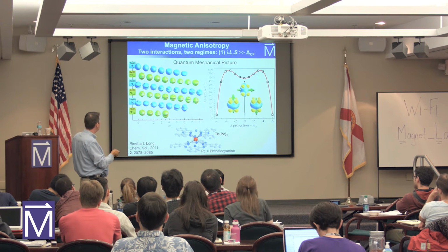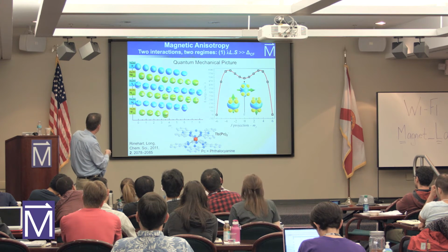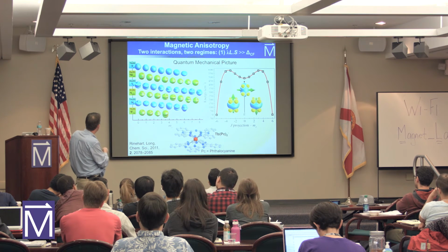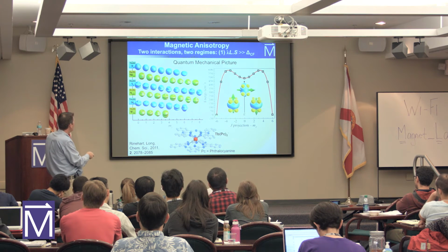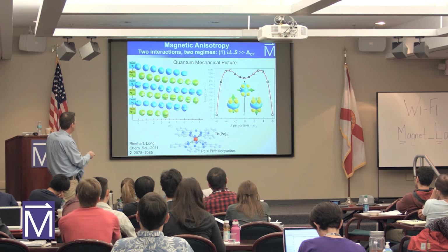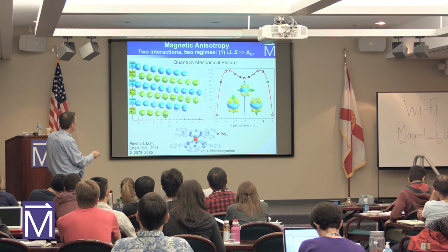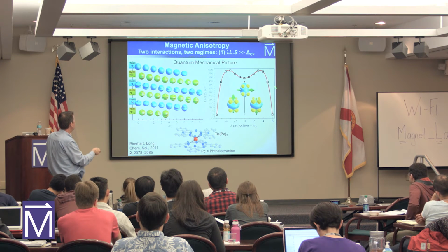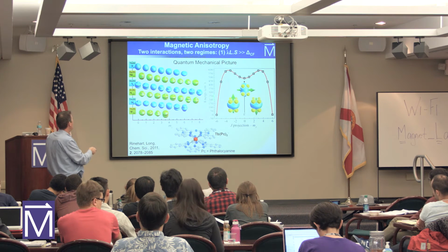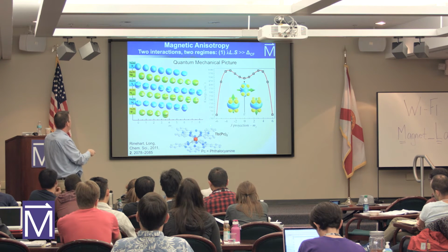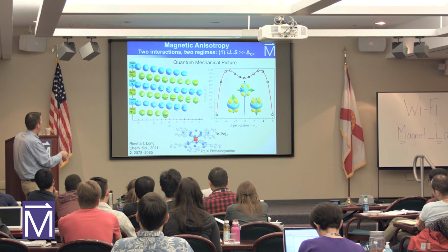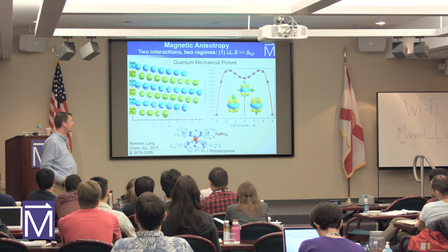In a quantum mechanical picture, this shows the shapes of all of the different M sub S states of these different orbitals for 6 of the lanthanides. And so now you've got a discrete energy spectrum. This is for terbium, minus 6, plus 6, and all the states in between. So it's not a nice smooth barrier. There's a little minimum up here, but you can see you have exactly what you want. You have about 450 wave numbers separating the lowest state and the barrier.